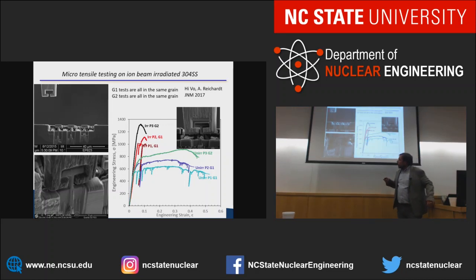But so we make these T-shaped features and then pull on them and make tensile tests at the same length scale. And we see something very similar: unirradiated material shows a lot of strain with some very small load drops along the way. And the irradiated material shows a high yield stress, very low strain, and a couple of very distinct load drops, and then they just break. Interestingly, even on a micro scale, these numbers are actually reasonable. So 304 stainless steel, unirradiated, has like 50% or so total elongation. Irradiated, in this instance, got less than 10, which is very similar to what you'd see in a macroscopic test.